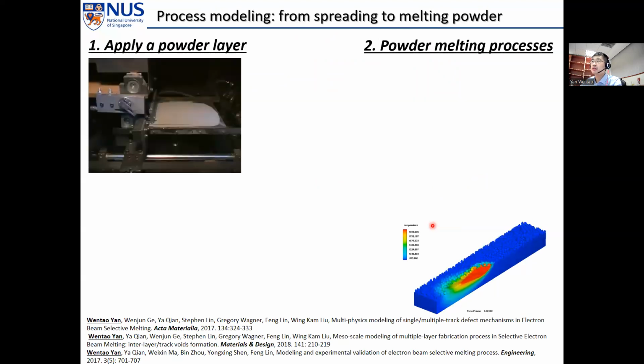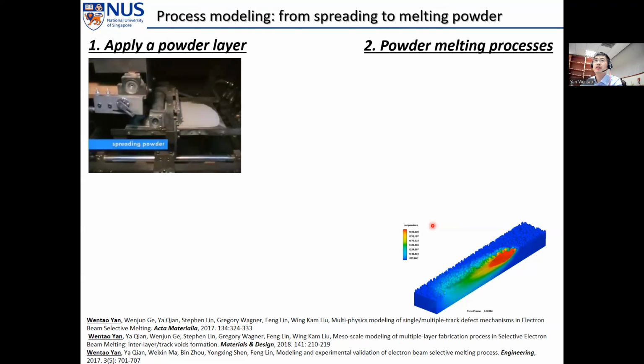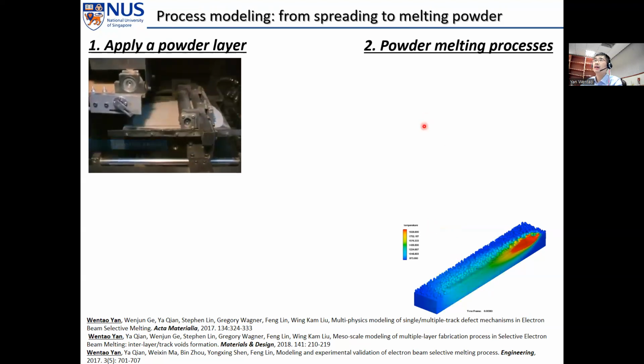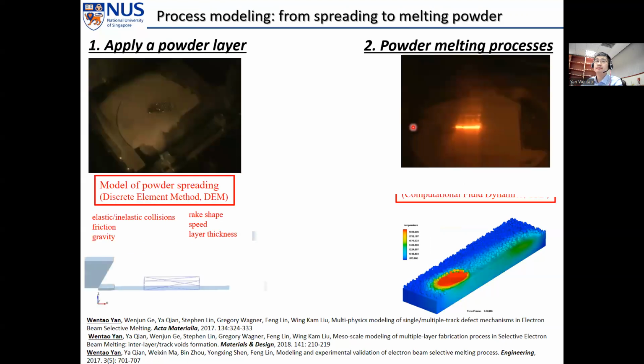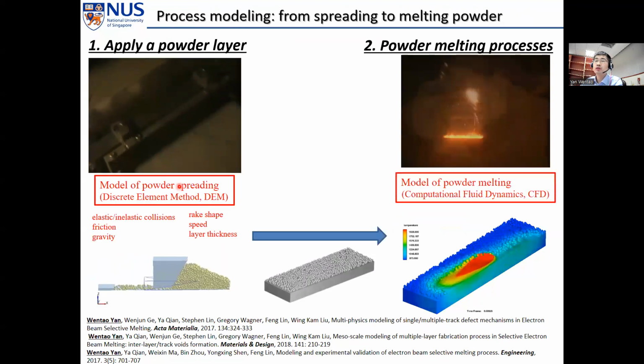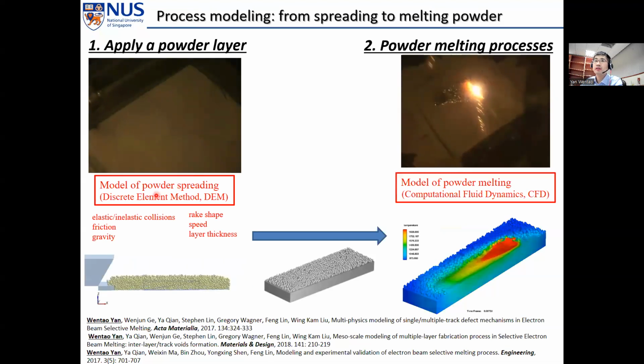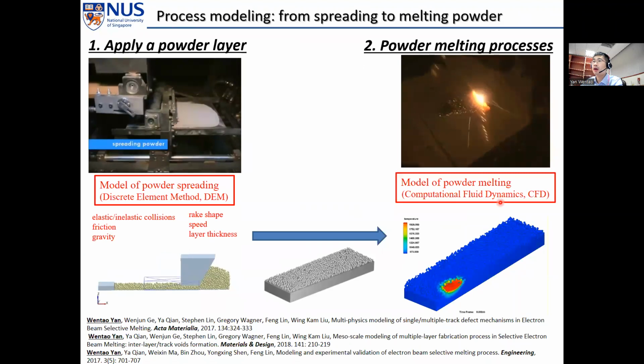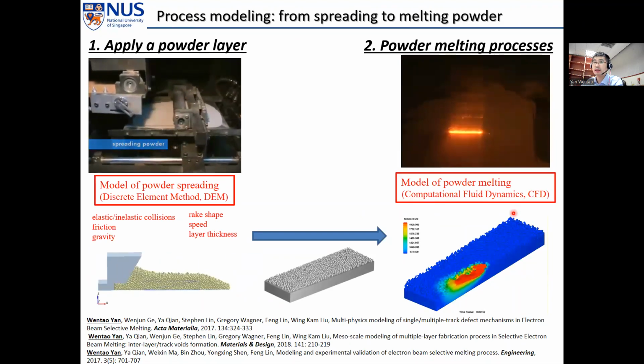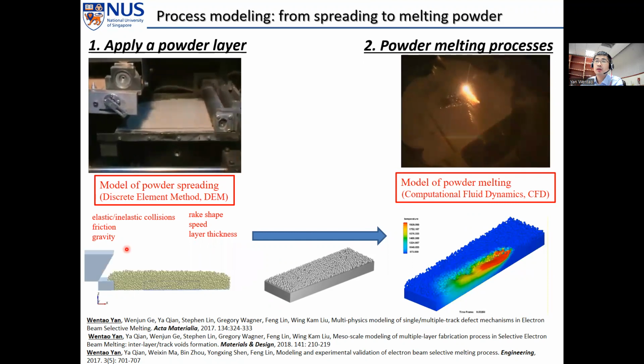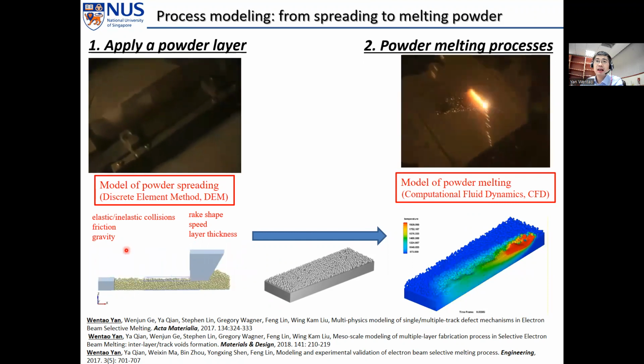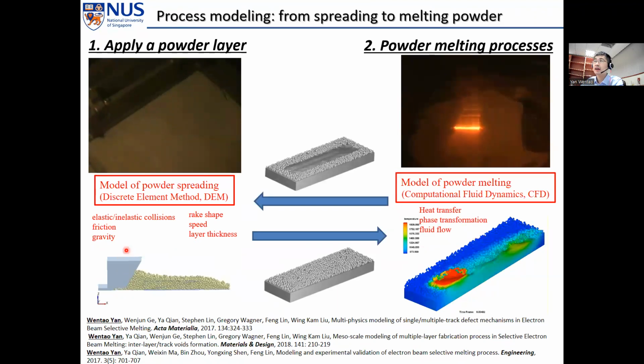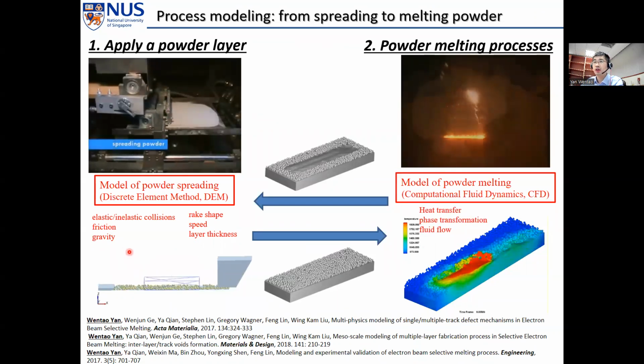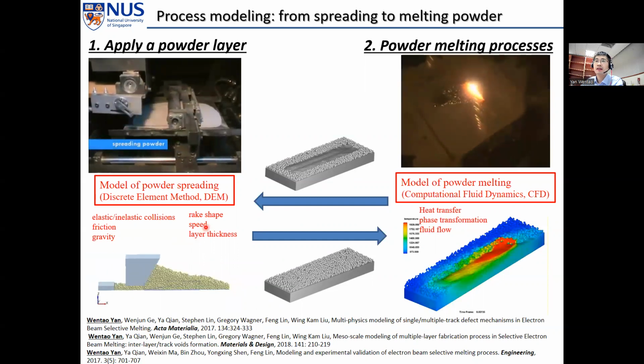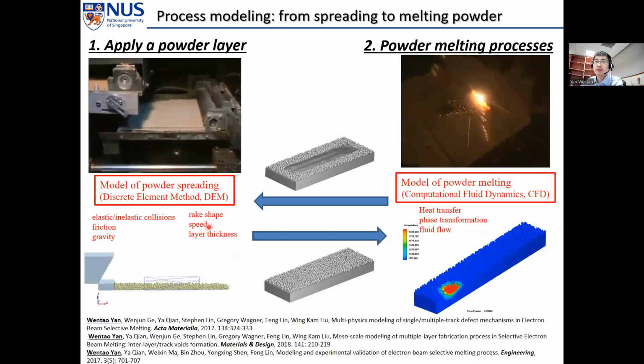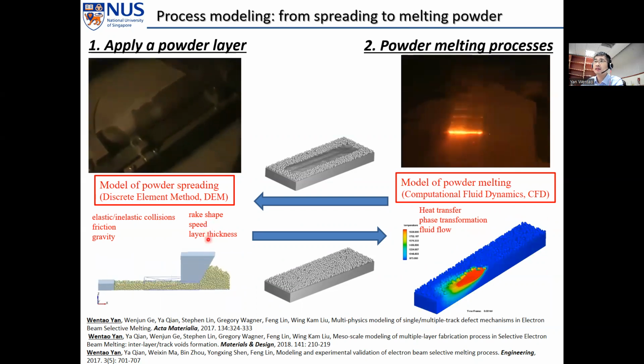And for the manufacturing process, there are two major procedures. First is applying a powder layer. Second is the powder melting process. So correspondingly, we built two models: powder spreading using the discrete element method, and powder melting using computational fluid dynamics. In the powder spreading model, we include the elastic and inelastic collisions, friction, gravity, and also van der Waals force. And we can investigate the influence of the rake shape, speed, layer thickness, and powder size distribution.